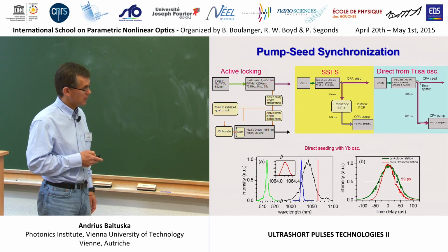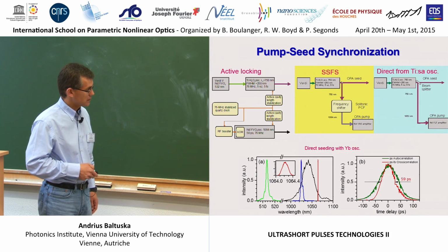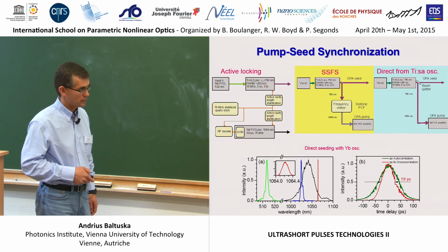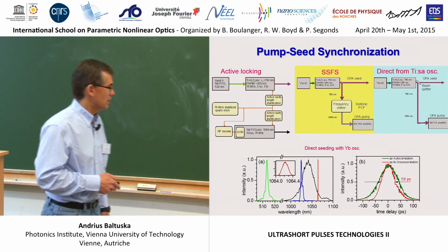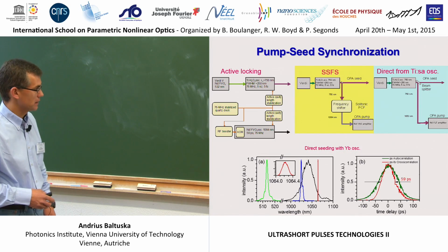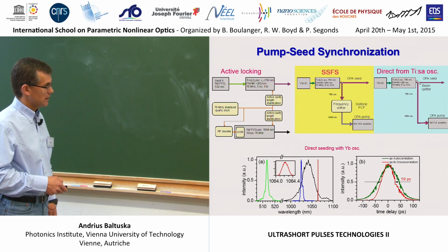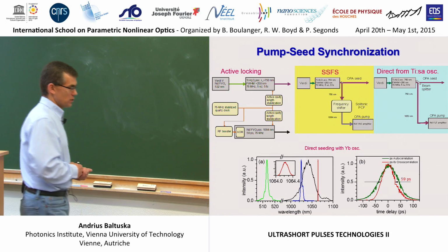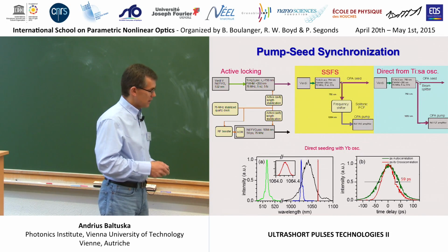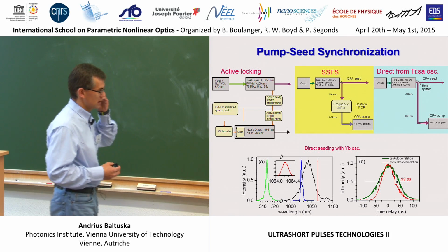you could also think about seeding it directly at the wavelengths of 1 micron. And that's what we've been doing for the past 8 years. So you rely on the fact that the bandwidth of some ytterbium materials is quite wide. And it covers 1030 nanometers where broadband ytterbium materials are, and 1064 nanometers where neodymium YAG, the picosecond material, is.